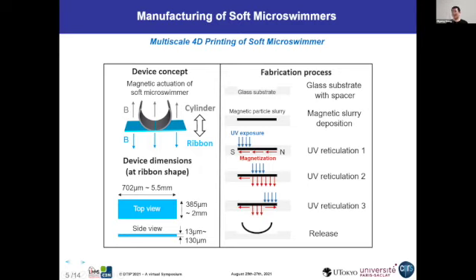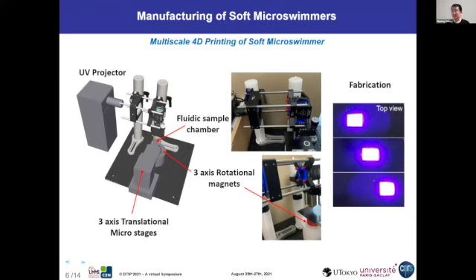And then once this part is fixed and reticulated, we do the second part of magnetization and reticulation by changing the magnetic field direction. And then by sequential UV reticulation, we can achieve these soft transformable microswimmers. The manufacturing system consists of a UV projector, which is used to generate the UV exposure pattern.